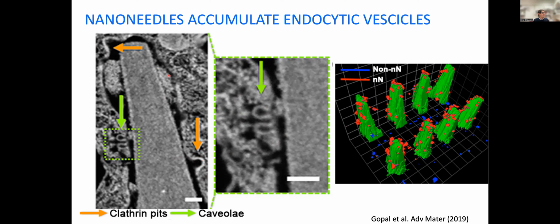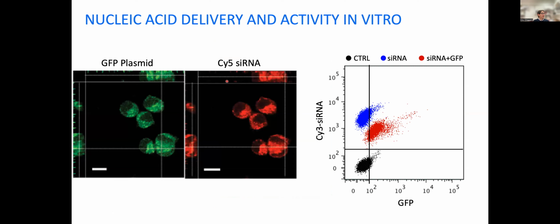And indeed, when you interface cells in this way and you get these significant membrane deformations, you end up having significant delivery of nucleic acids into the cells. In this case, we were doing it with a plasmid that was coding for the GFP protein and an siRNA that was targeting GAPDH and was labeled with Cy5, and we were co-delivering them from the needles into cells. And we could see that you can get up to 90% efficiency in the delivery of both the siRNA and the GFP.